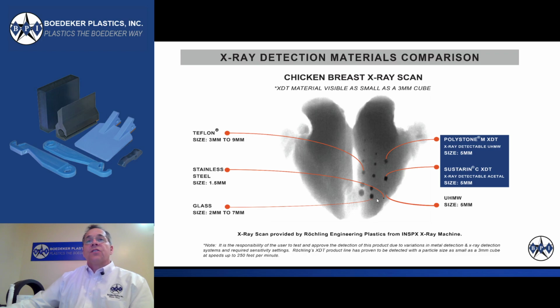By contrast, over here is a piece of ultra-high molecular weight polyethylene, virgin grade, with no detectability additives, 6 millimeters in size, and you can barely see the shadow. That obviously would not show up on the detection system and would just move right on through and not be flagged. So hence where the danger comes in with standard plastics.